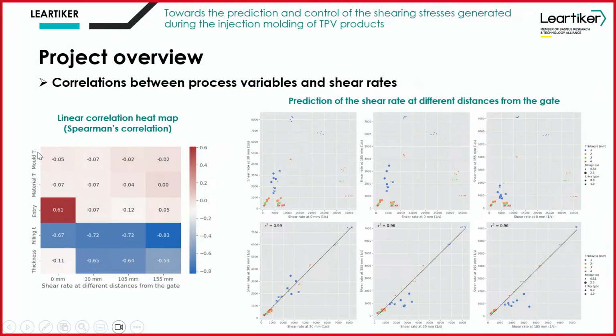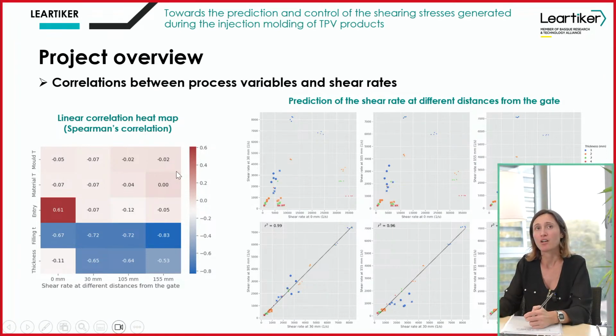In this case, we have analyzed the effect of the mold temperature, always considering the recommendations of the material supplier. The supplier recommends not to exceed 70, so 30 to 70 are the limits. So we analyzed what happens if we injection mold with a mold temperature of 30 degrees or 70 degrees. And what we observed is that the material and mold temperature have little effect on the shear rate. So it seems that they are not the key parameters to control if we want to tune the final properties of these materials.